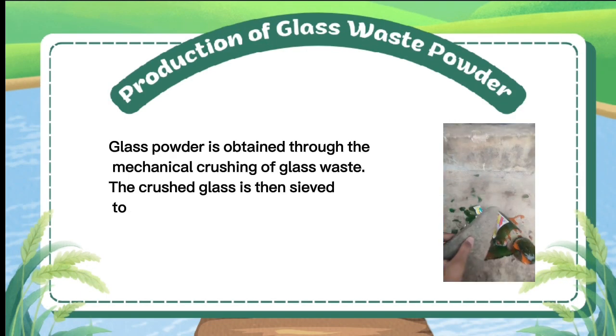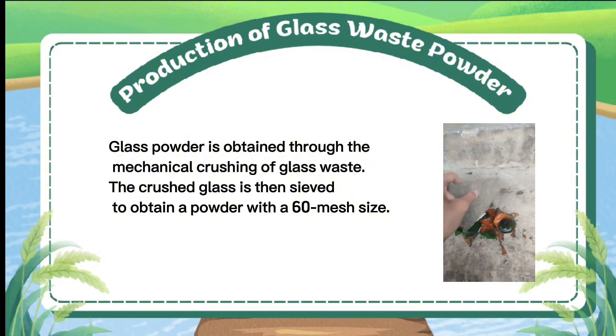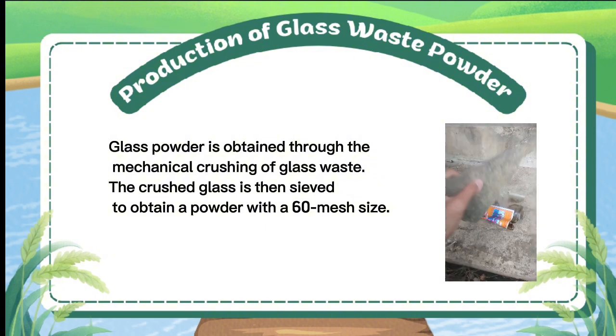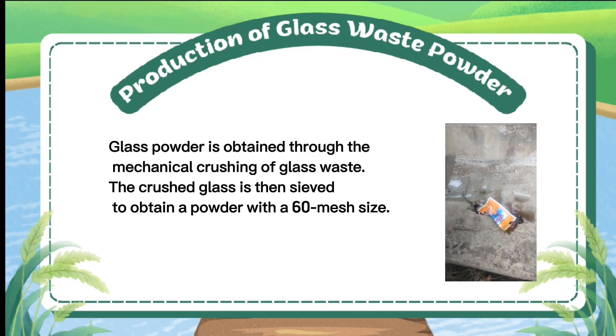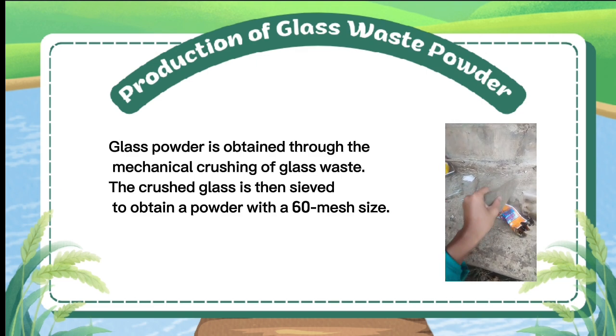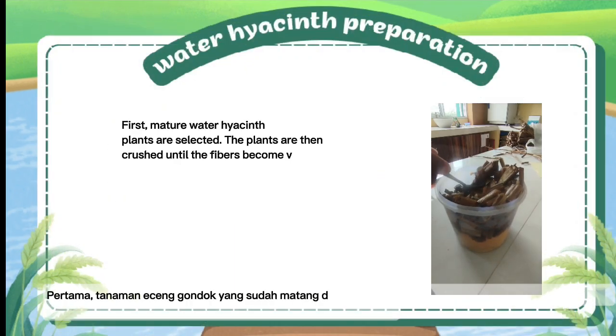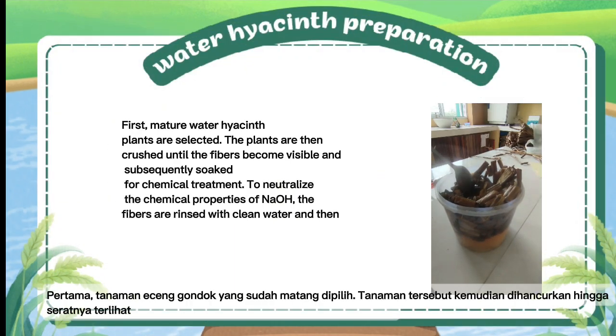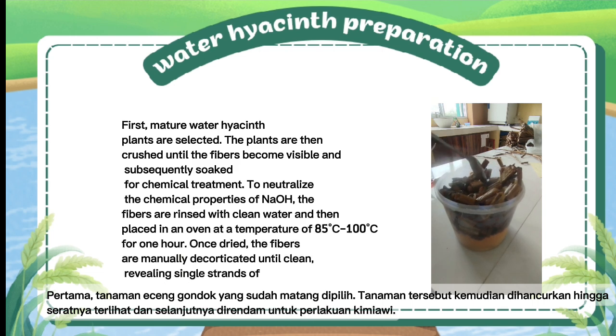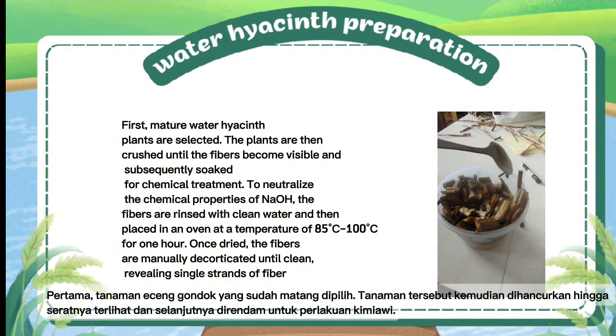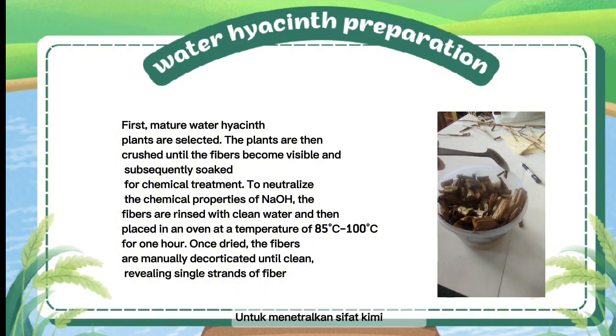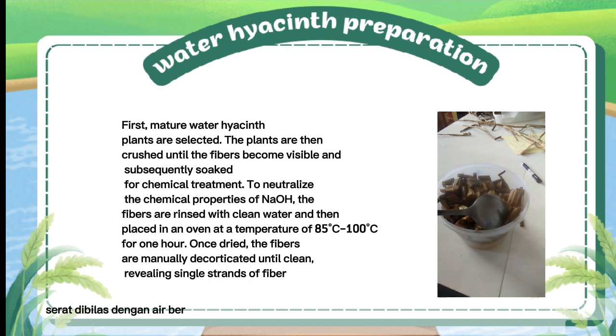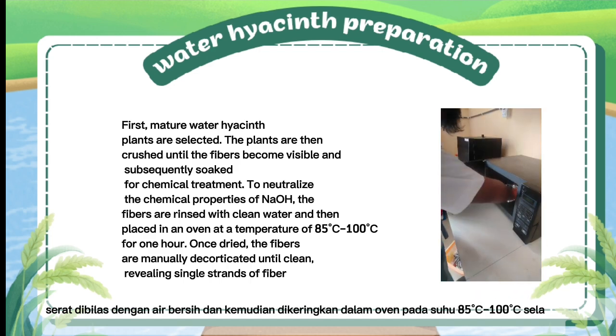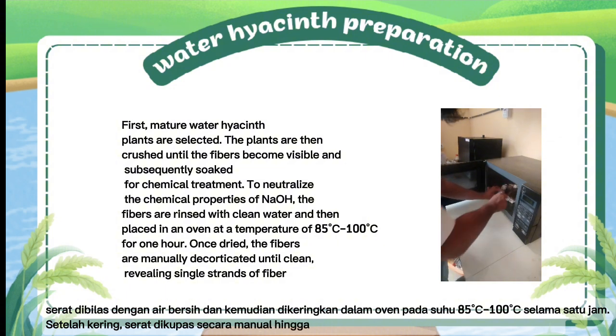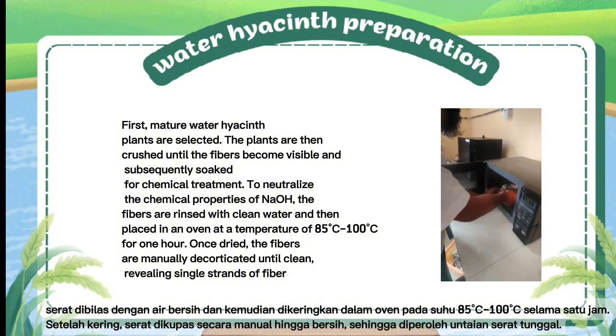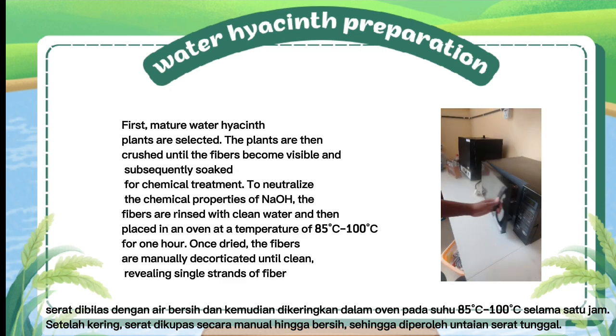Production of glass waste powder. Glass powder is obtained through the mechanical crushing of glass waste. The crushed glass is then sieved to obtain a powder with a 60 mesh size. Preparation of water hyacinth fiber. First, mature water hyacinth plants are selected. The plants are then crushed until the fibers become visible and subsequently soaked for chemical treatment. To neutralize the chemical property of NaOH, the fibers are rinsed with clean water and then placed in an oven at a temperature of 85 to 100 Celsius for an hour. Once dried, the fibers are manually decorticated until clean, revealing a single strand of fiber.